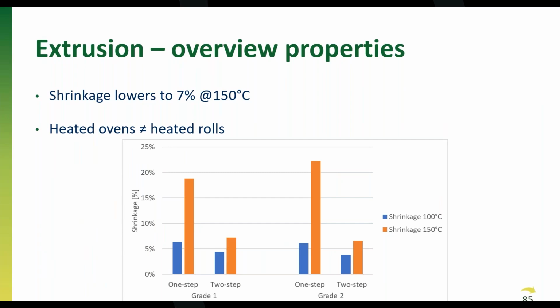An overview of the properties. First, the shrinkage, and later in the next slide we see the mechanical properties. So the shrinkage here divided over 100 and 150 degrees, and we have done this for two reinforcement grades, so two high melting grades, each in a one-step and a two-step drawing process. You can see that there is a huge difference between the one and two-step drawing process for each of the grades. We can see that at 150 degrees, the shrinkage really lowers drastically from, for the first grade, around 18% to 7%. For the second grade, an even larger difference is observed, coming from 22% to only 6% with the two-step drawing process.